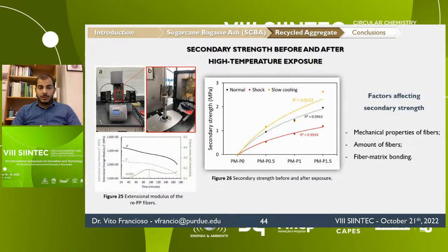The thermal shock, which is the red curve, reduced this secondary strength with respect to the normal condition. And this can be related to the fact that the thermal shock samples were tested in hot conditions, affecting the mechanical properties of the fibers. Nevertheless, in samples tested after slow cooling, the fibers could recover all their strength and contribute again to the strength of the composite. Not only that, it improved, suggesting an improvement in the fiber matrix bond.